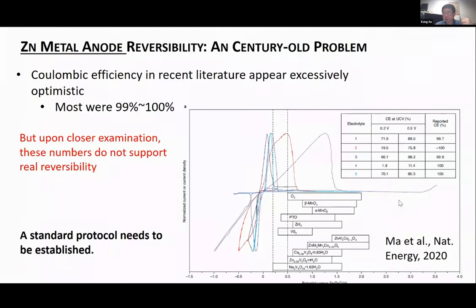But if you examine those data closely, you'll see that those are true, authentic data, but they were obtained under conditions which are not realistic for practical application. For example, the highest coulombic efficiency number, 100% we see in the literature, actually was achieved by huge polarization on both the negative side and positive side. In order to completely strip the zinc deposit there, they polarized the zinc metal anode up to nearly 2 volts.